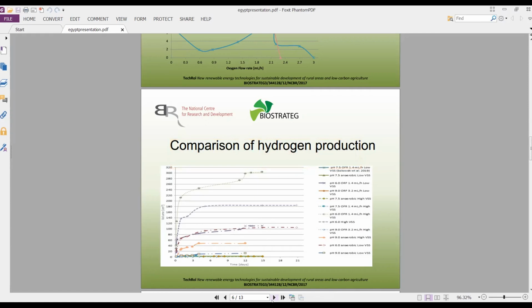And here we have the cumulative hydrogen production, and we observe that hydrogen is the highest for 0.8, the cumulative, so overall hydrogen production. We also checked basic pretreatment, but pH 9 doesn't give interesting results.